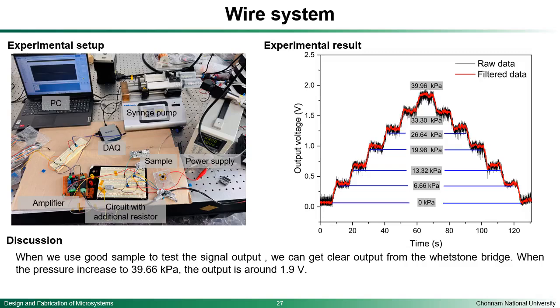Because our sensor is not really working well, we use another team's good sensor to continue some basic tests. Here we borrowed another team's sensor. We increase the pressure from 0 kilopascal to 39.96 kilopascal, which is close to 300 millimeter. With each step we change the pressure value by around 6.6 kilopascal. Here we can clearly see that when we apply the pressure, the output voltage clearly changes.